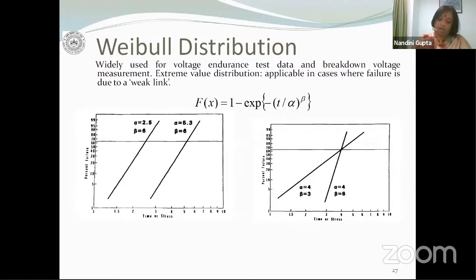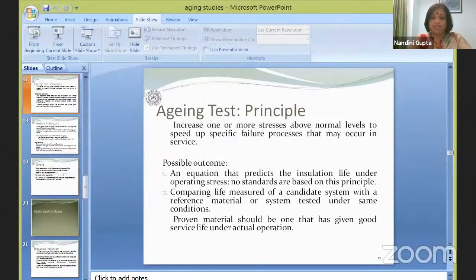Actually, with Weibull distribution, you can have a 2-parameter Weibull distribution and a 3-parameter Weibull distribution function. In our case, we don't need to bother about the third parameter, so we stick to the 2-parameter Weibull distribution, which is given by F(x) equal to 1 minus e to the power minus (t/alpha) to the power beta. Alpha and beta are the parameters of the Weibull distribution. Alpha is analogous to the mean value of a normal distribution. So it gives me the expected value of the parameter, the expected breakdown strength if you're talking about breakdown strength. And beta is analogous to the standard deviation. So beta gives me the spread of the data.